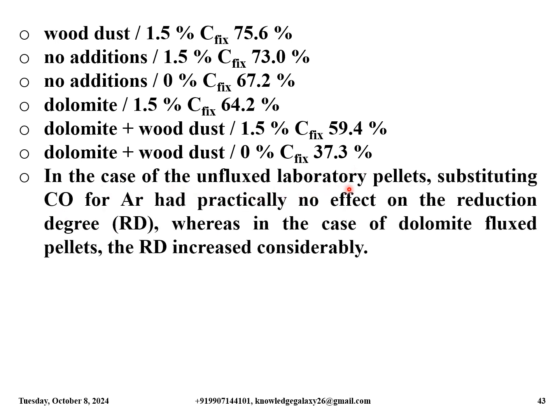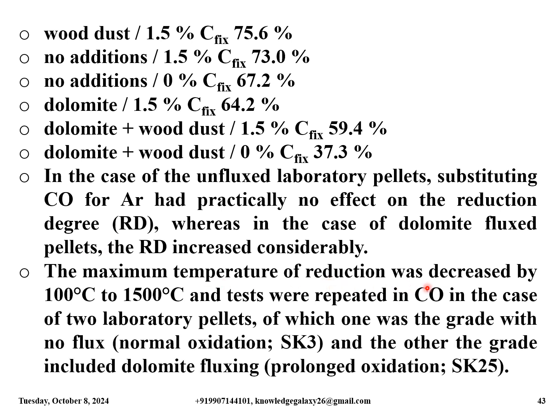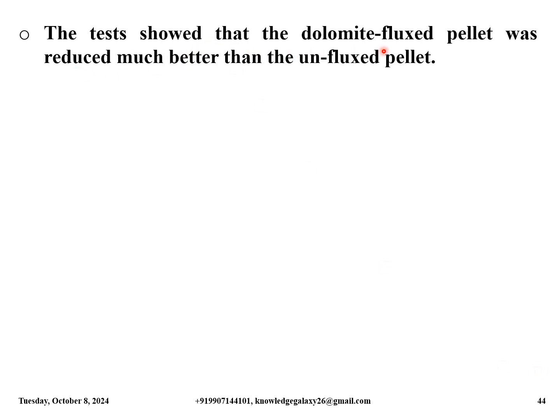In the case of the unfluxed laboratory pellets, substituting carbon monoxide for argon had practically no effect on the reduction degree, that is RD, whereas in the case of dolomite fluxed pellets, the reduction degree increased considerably. The maximum temperature of reduction was decreased by 100 degrees Celsius to 1500 degrees Celsius, and tests were repeated in carbon monoxide in the case of two laboratory pellets, of which one was the grade with no flux, normal oxidation, SK3, and the other, the grade included dolomite fluxing and prolonged oxidation, SK25. The test showed that the dolomite flux pellet was reduced much better than the unfluxed pellet.